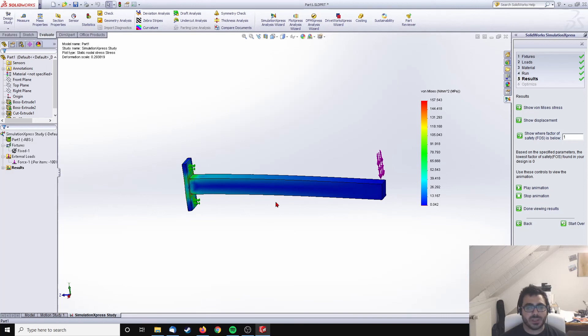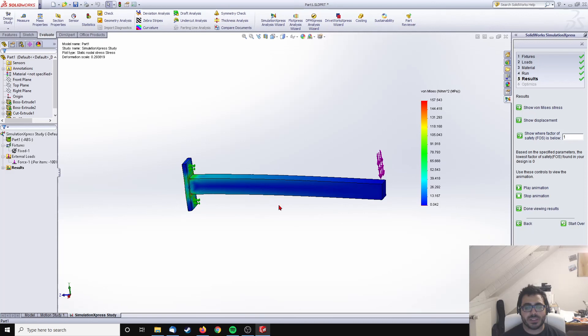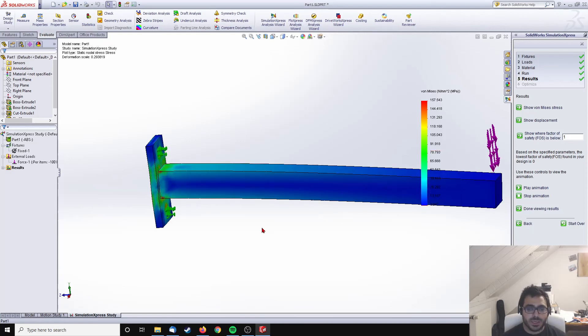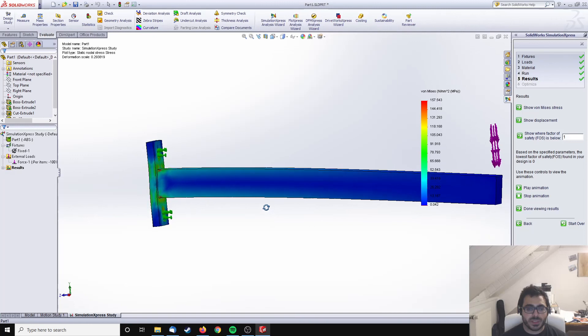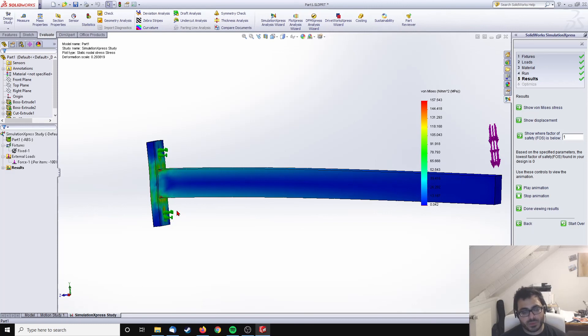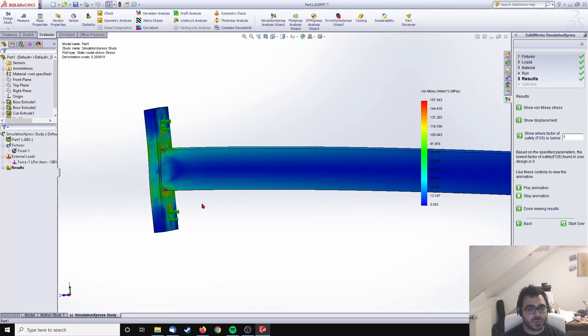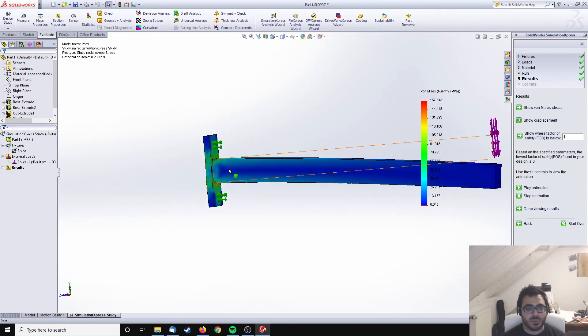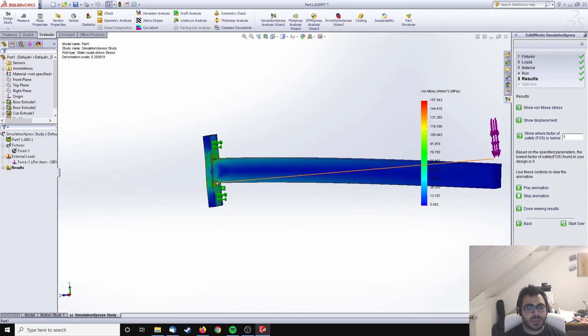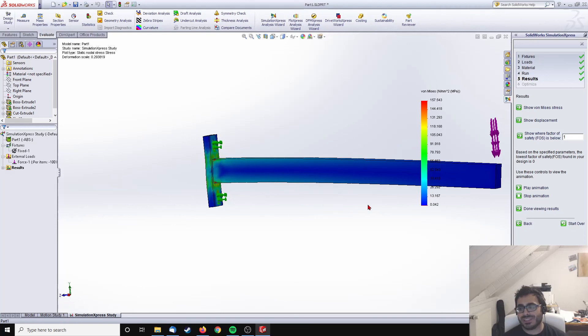Definitely in this case it will be better if you have the layers in this orientation so you don't have separation stresses but shear stresses. If you print this in this direction you need a lot of support here because of this area. So it would be useful to try to move this geometry down to the bottom so it lays on the print bed and then you add these two screws above it. That will actually work better.